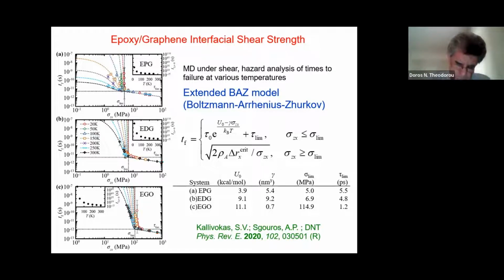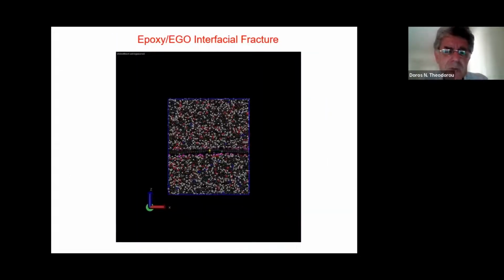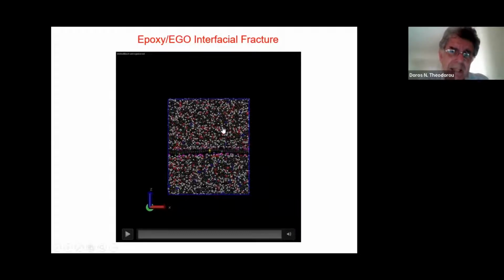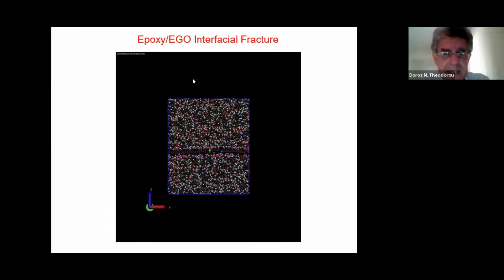And if such an association breaks, this is the onset for a failure of the interface, which is more localized than in the case of the other types of interface. Here is what happens pictorially when you have a graphene oxide inside the epoxy, and you impose a stress which is lower than the limiting stress.